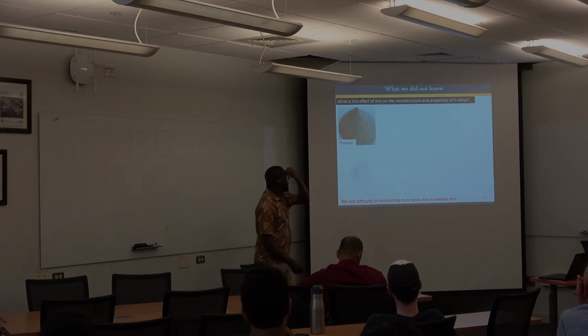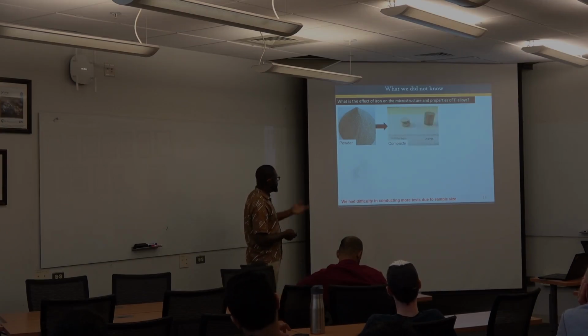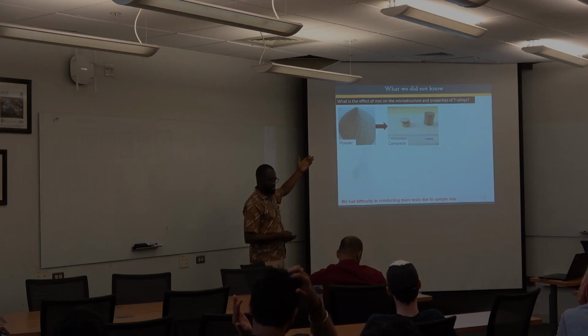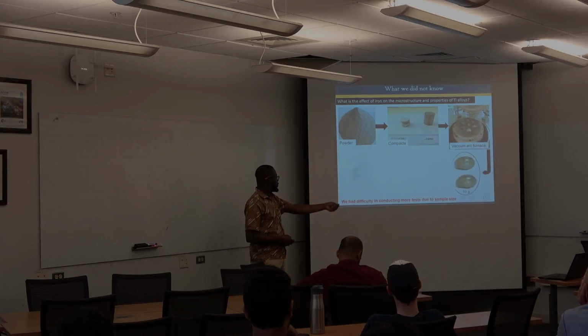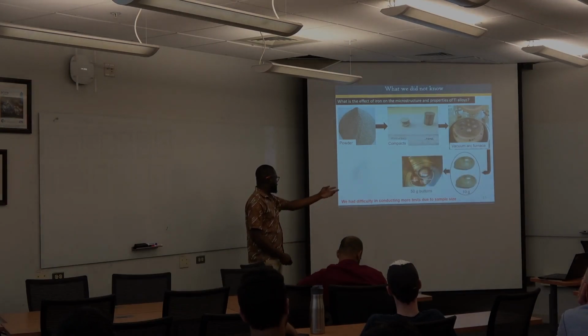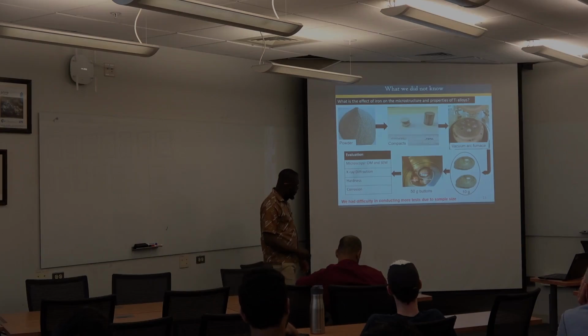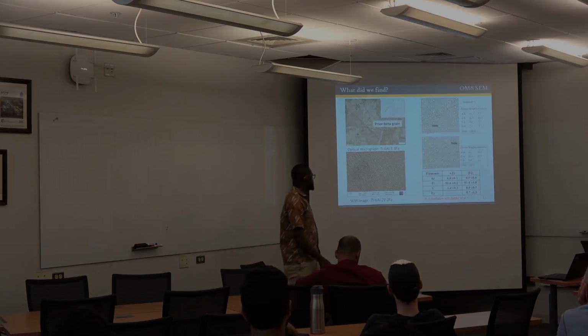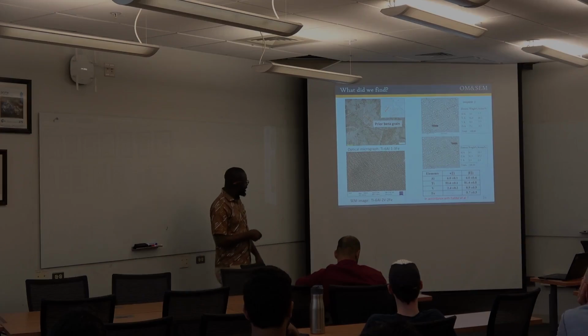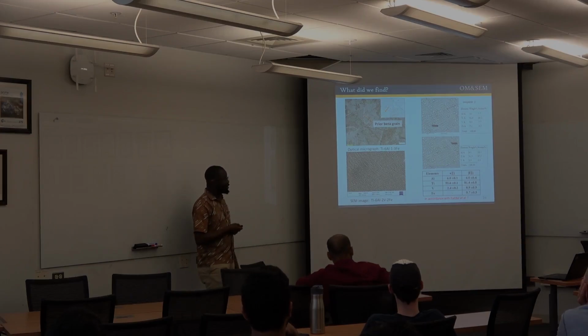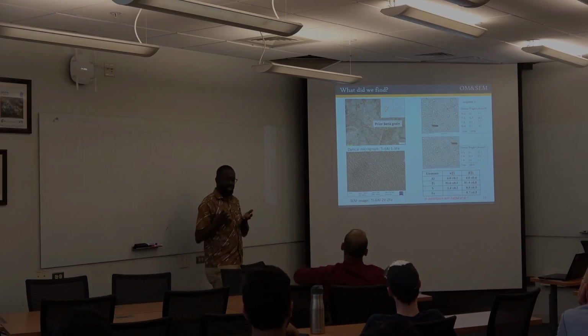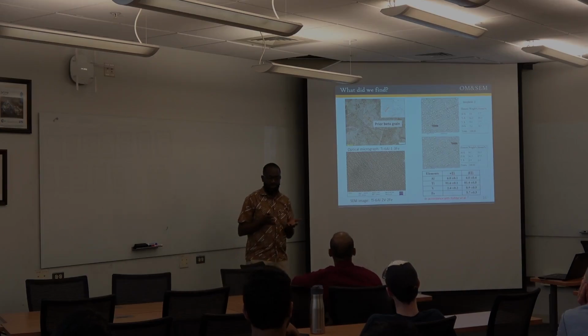To take you through some of the things that we did, we got the powders with the different compositions that we compacted, produced pellets of 10 grams and 50 grams, and then we got the basic results. So what did we find? Even though we have iron in our alloys, we essentially have alpha and beta phases in the microstructure.